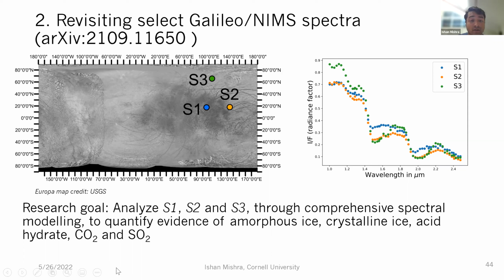And so I'm showing here where those 3 spectra are coming from. S1, S2, and S3. So S1 was coming from this very visibly dark part of Europa's trailing hemisphere, where most of the irradiation damage exists and most of the non-water ice material is thought to be present. And then S2 and S3 are coming from just outside these regions, but from different latitudes. And this is what those three spectra look like.